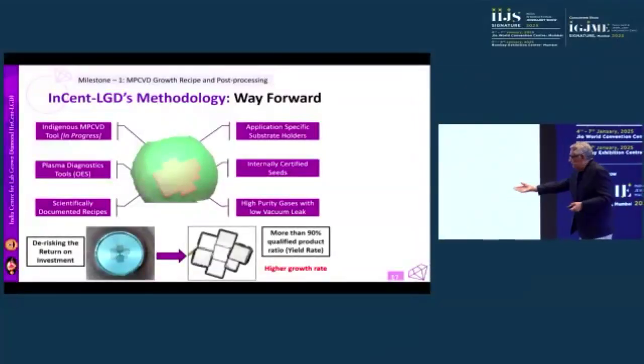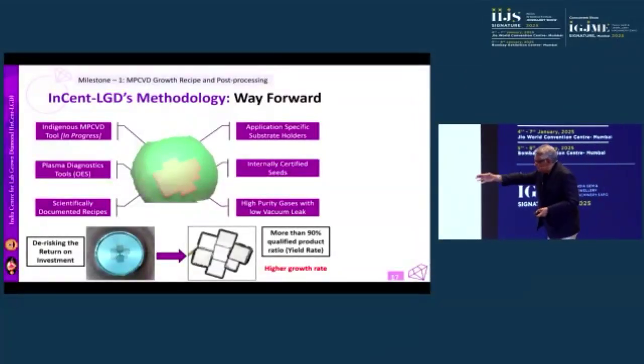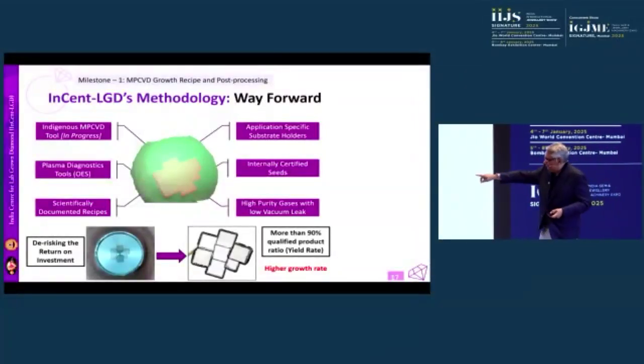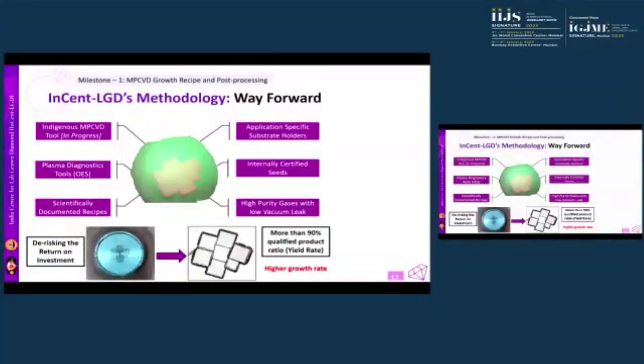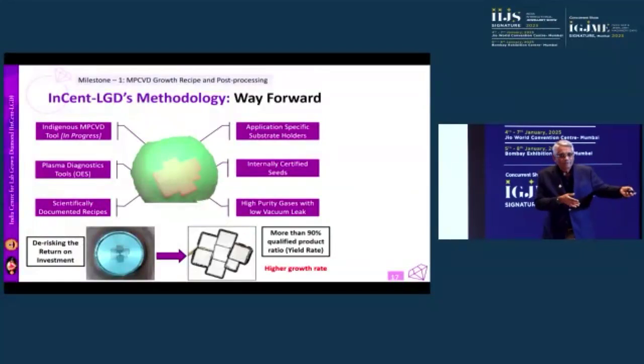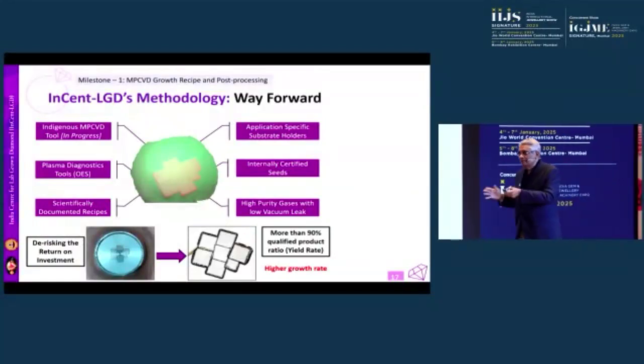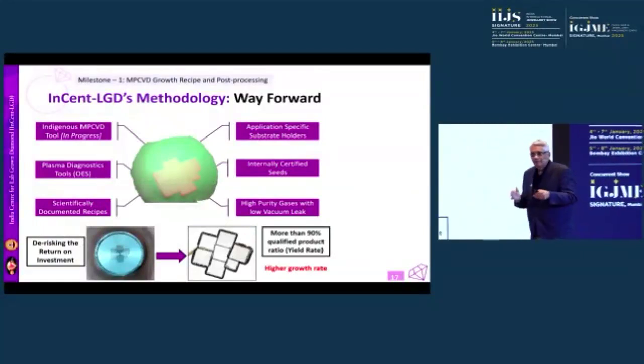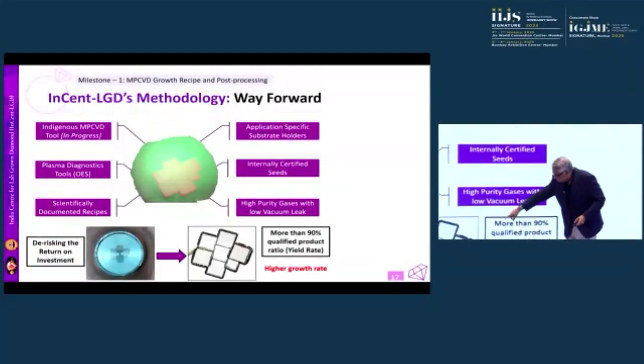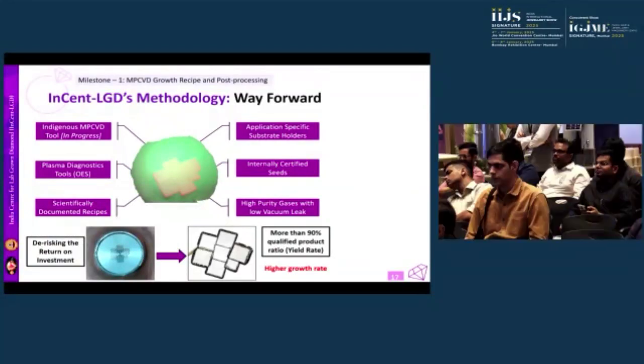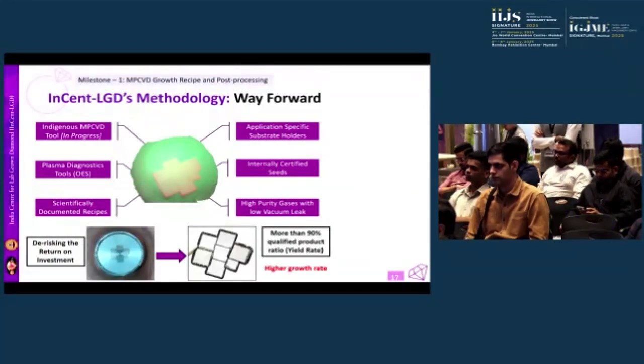All right. And look at this, what we have done. This is just an example of taking care of some of these points, right? By looking at the initial quality of the seed, by making sure that we use a proper high purity gas, you see that all the seeds that we use turn out to grow good quality diamond on them. So the yield is almost 90 or more than 90%. That's what we need finally, right?